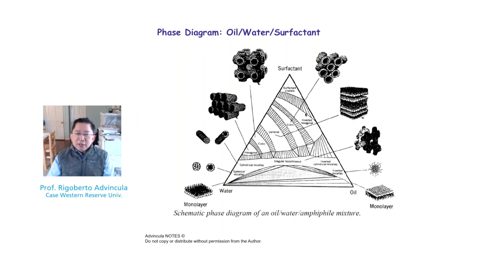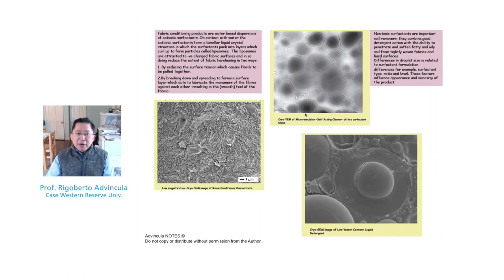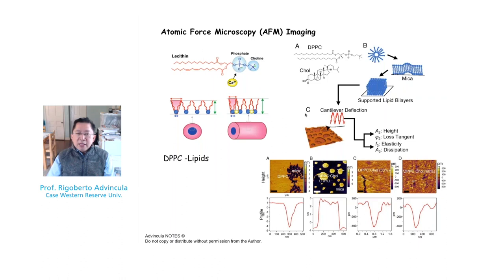Surfactants and these different mesophases are real and can be observed by techniques like cryo-transmission electron microscopy. In cryo-TEM you can actually see spherical micelles, vesicles, or even multilamellar vesicles forming an onion-like structure. SEM is also a good technique to observe micelles and vesicles formed on surfaces like fabric. However, to see molecular orientation and packing of surfactant films, atomic force microscopy imaging is a very powerful technique, for example in the study of surface-supported lipid bilayers on flat surfaces like mica.